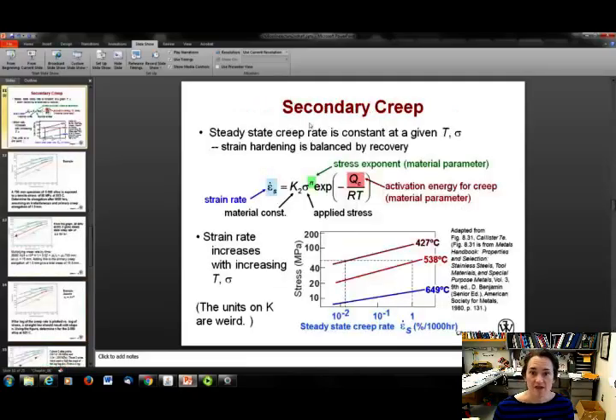Okay, so let's talk more about that secondary creep regime, okay? Your steady state creep rate is actually constant at a given temperature and stress. You're at that point where the strain hardening is balanced by recovery and you've got that constant looking slope. Okay? So given a temperature, okay, your exponential dependence of your temperature is here, so you have the activation energy for the creep, and as long as that temperature is held constant, this exponential term here is constant. It's e to the minus Q over RT, and that's the activation energy for the creep there, that Q, and then there's your temperature, okay? Now, your strain rate is the strain, which remember is the change in length over the length.